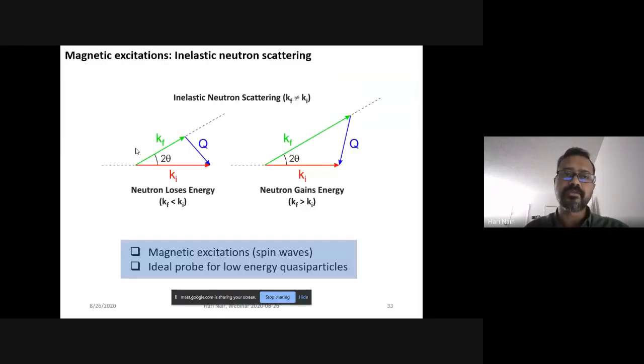Once we had this information, we went to look for magnetic excitations. Why? Because we want to know if there is any fancy excitation like an anyon or something of that sort. So you measure what is known as spin waves. The previous scattering experiment is different because that is an elastic scattering event, because there is no change in energy that we are going to measure. So it is completely elastic. The energy of the incoming neutron is the same as the energy of the outgoing neutron in that case.